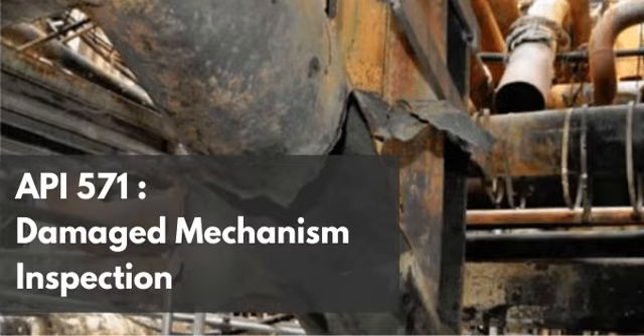Exactly. It insulates the inside of the tube, meaning the operator has to fire the furnace harder and hotter on the outside just to get the same amount of heat into the process fluid on the inside. Right. They are wasting fuel, the efficiency drops, and the tube metal itself gets dangerously hot. So the operator decides it is time to clean the tube. Makes sense. They take the unit offline from normal production, and they run a decoke cycle. Their goal is to intentionally burn off and remove that solid coke buildup from the inner diameter of the tube.